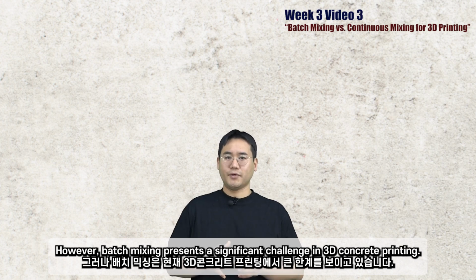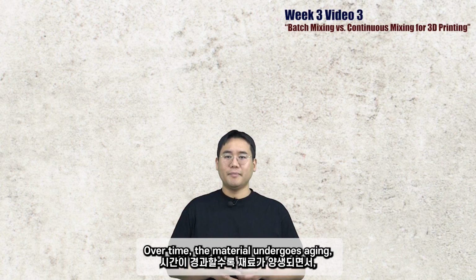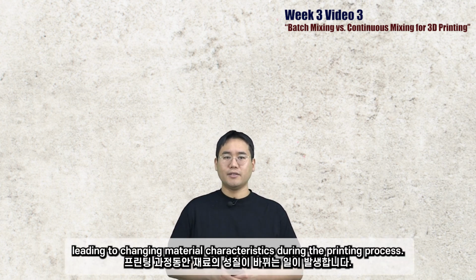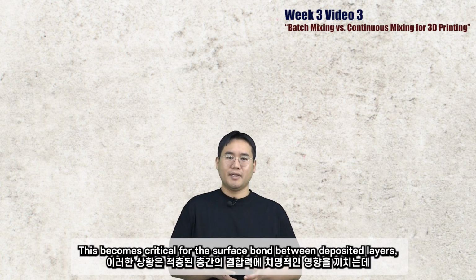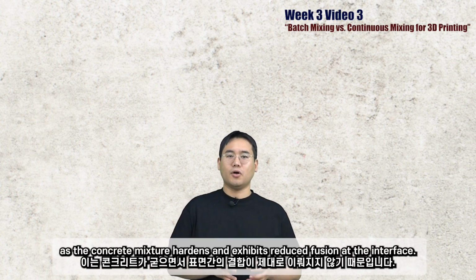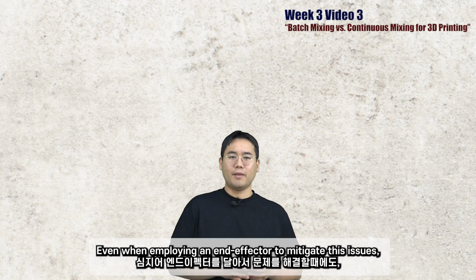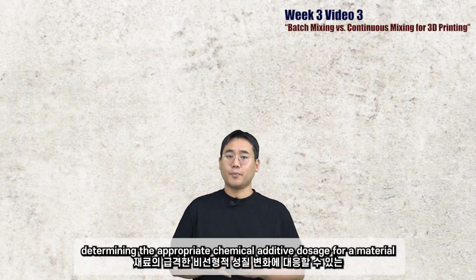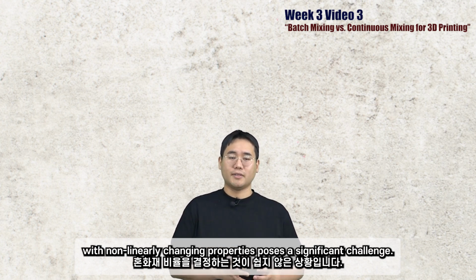However, batch mixing presents a significant challenge in 3D concrete printing. Over time, the material undergoes aging, leading to changing material characteristics during the printing process. This becomes critical for the surface bond between the deposited layers, as the concrete mixture hardens and exhibits reduced fusion at the interface. Even when employing an end effector to mitigate this issue, determining the appropriate chemical additive dosage for a material with non-linearly changing properties poses a significant challenge.